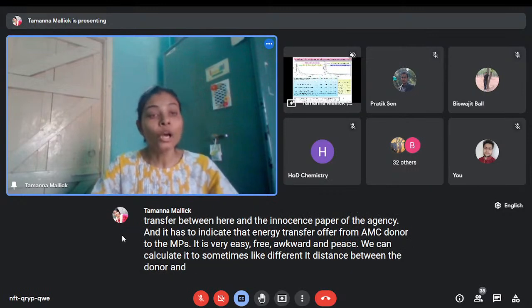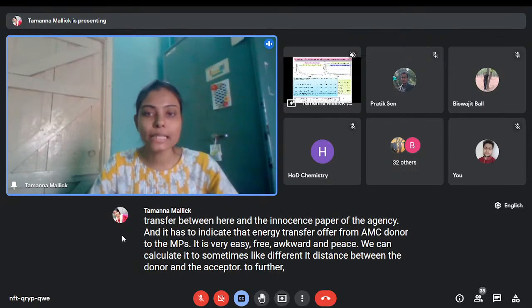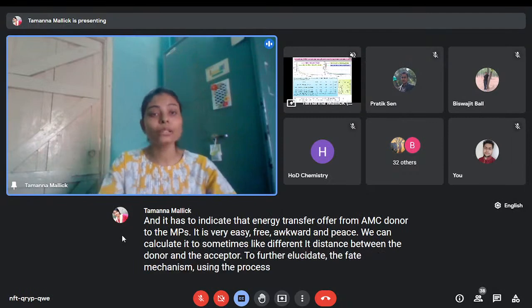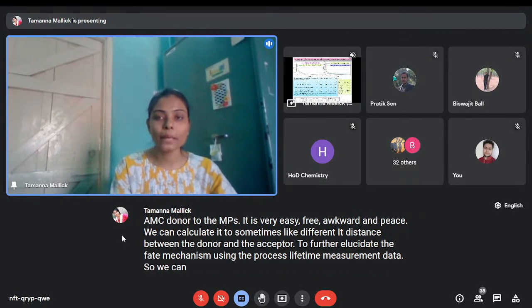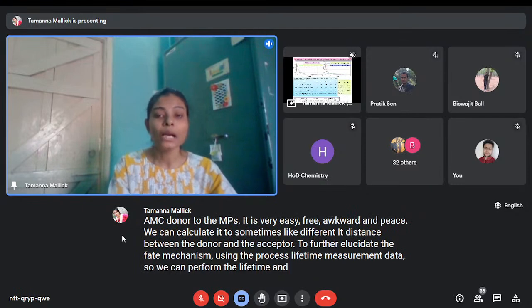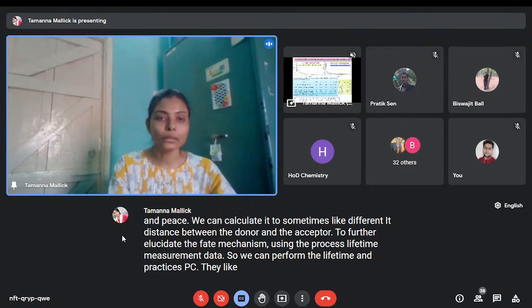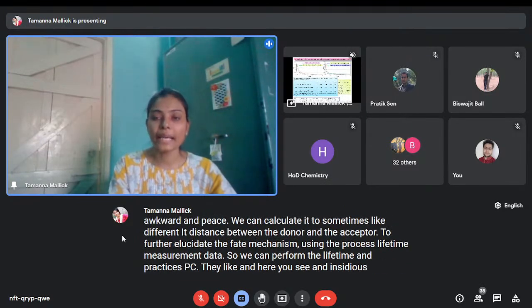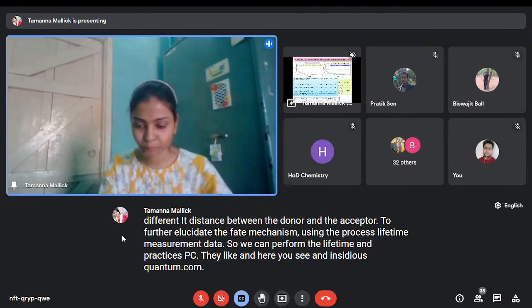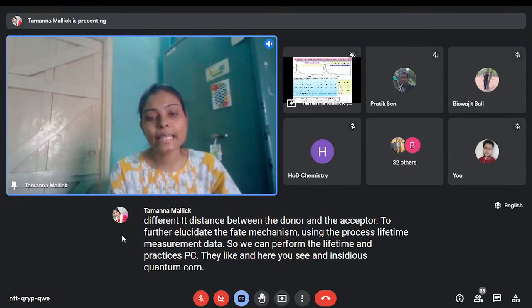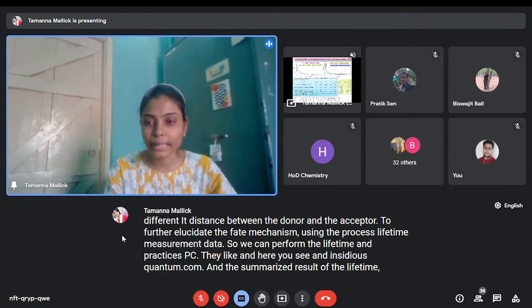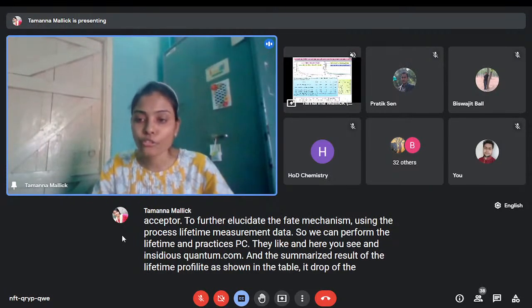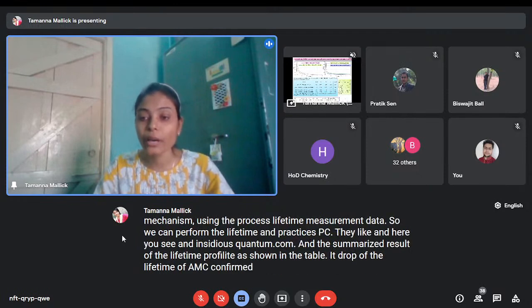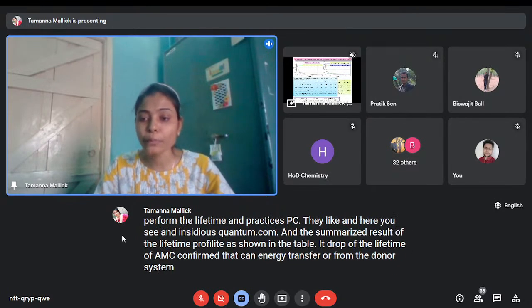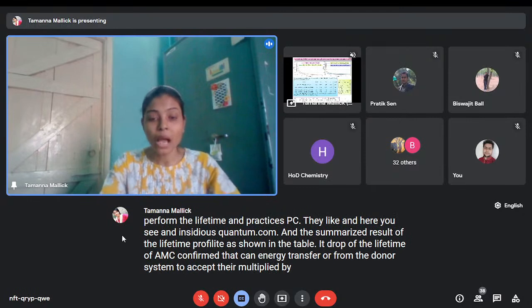To further elucidate the FRET mechanism using the fluorescence lifetime measurement data, we perform the lifetime measurement by TCSPC. And here the AMC, AMC-CdS quantum dot, and the MPA and AMC-CdS quantum dots are compared. The summarized result of the lifetime profile is shown in the table. A drop of the lifetime of AMC confirmed that an energy transfer from the donor system to the acceptor moiety is probable by the FRET mechanism.